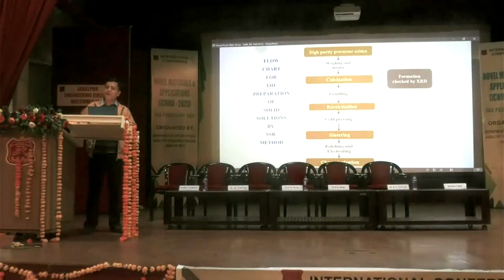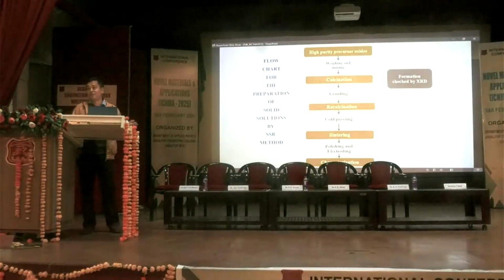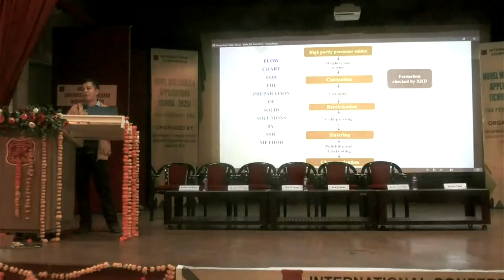Like if you need the powder in the form of a pellet, suppose you want to do electrical measurement, for which you need an LCR meter or impedance analyzer. You cannot put powder directly to measure the dielectric constant or the dielectric loss. For that, you need a pellet. So for the pellet, you put this material in a hydraulic press, generally a KBr press, and by pressing it, it comes out just like a tablet.